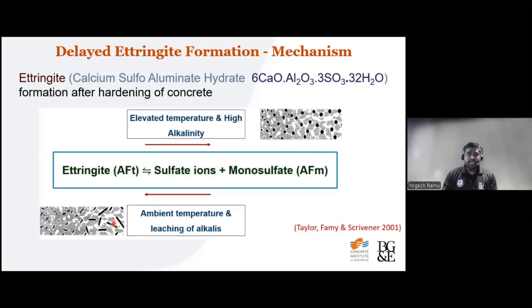So it doesn't have much space in the concrete to precipitate freely, and it's a highly voluminous hydrate to form in the structure. You can see needle-like structures in the graphical representation. What can happen is that this precipitation can push the concrete a little bit harder to create micro cracks in the system. So eventually, the internal cracking is bad. It can lead to durability related issues. That's why everyone is talking about DEF.